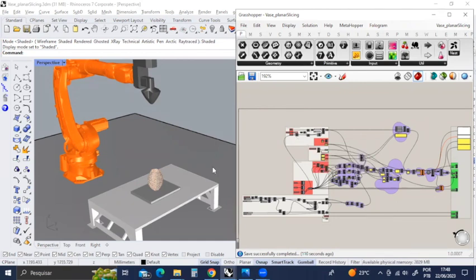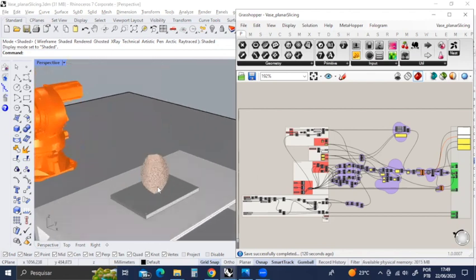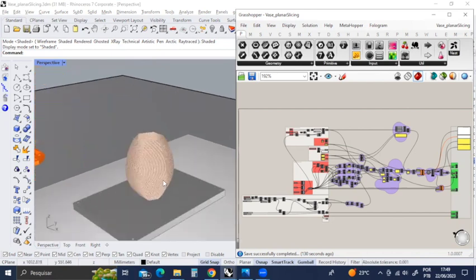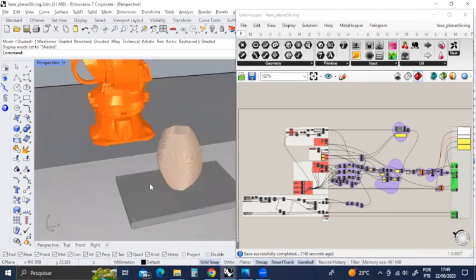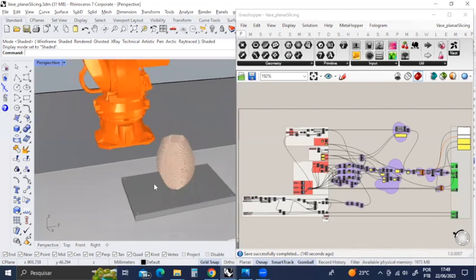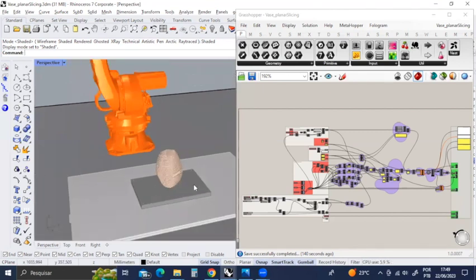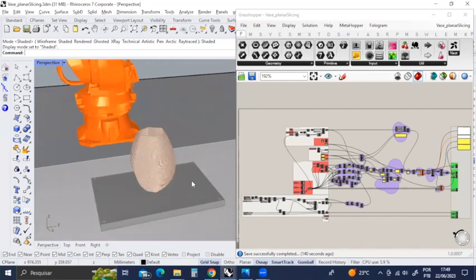The model is a work in progress to be parameterized in many deposition options for a variety of parts, being planar or non-planar. I will present you with the deposition process of a vase through laser metal deposition with wire technology. The robot is equipped with the Meltio tool for LMD-wire, and the setup is to contour the vase with a 3-bead layer of 1.2 millimeters height by 1 millimeter width for each bead.